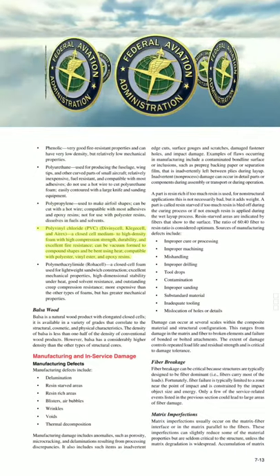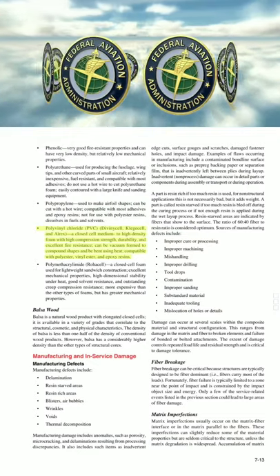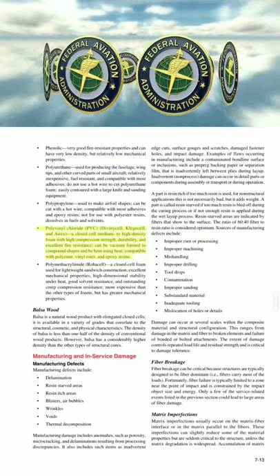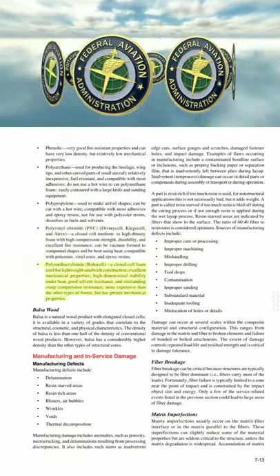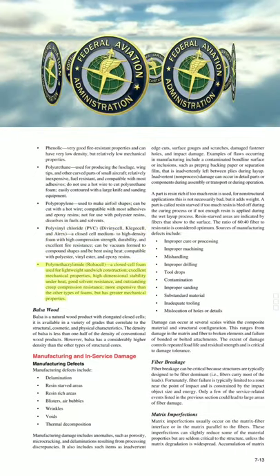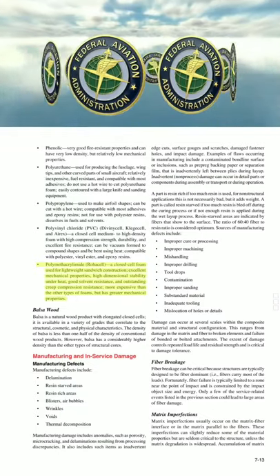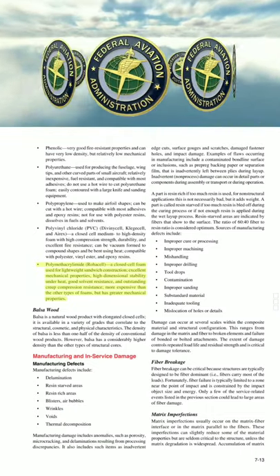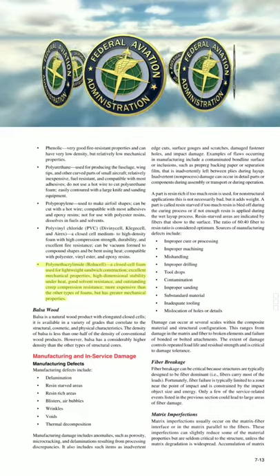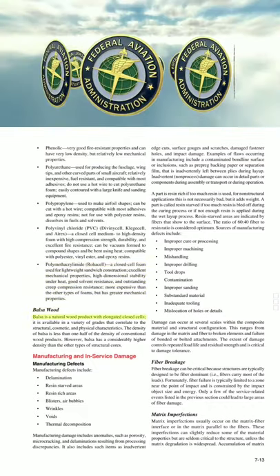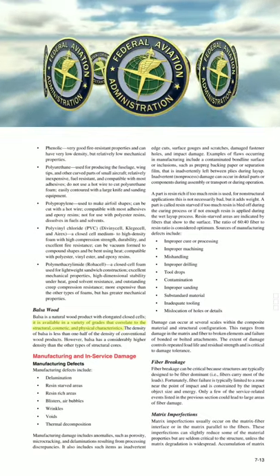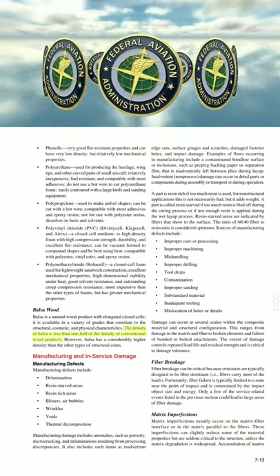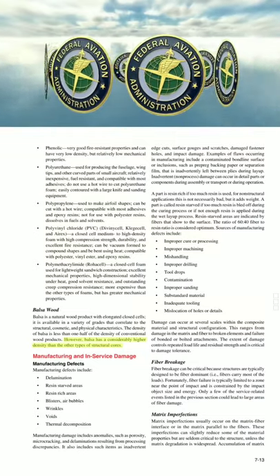Polyvinyl chloride (PVC) foam — Divinycell, Klegecell, and Airex — is a closed-cell, medium- to high-density foam with high compression strength, durability, and excellent fire resistance; can be vacuum-formed to compound shapes and compatible with polyester, vinyl ester, and epoxy resins. Polymethacrylimide (Rohacell) is a closed-cell foam for lightweight sandwich construction with excellent mechanical properties, high dimensional stability under heat, good solvent resistance, and outstanding creep compression resistance — more expensive but with greater mechanical properties. Balsa wood is a natural wood product with elongated closed cells, available in grades correlating to structural, cosmetic, and physical characteristics. Its density is less than half that of conventional wood products; however, balsa has a considerably higher density than the other types of structural cores.